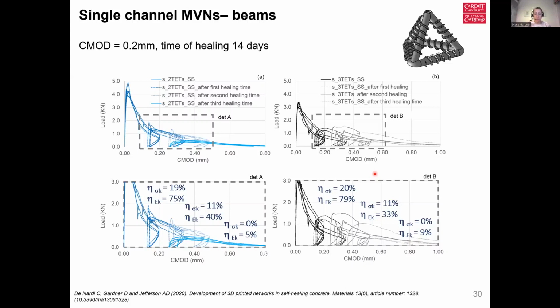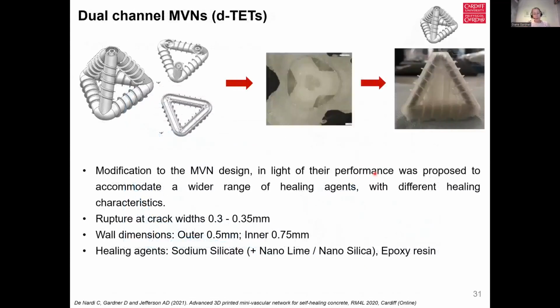Nonetheless, a recovery stiffness is still notable of 5% for our 2 minivascular network system and 9% for our 3 minivascular network system. In order to widen the applicability of these minivascular networks to a wider range of healing agents, we decided to undergo a bit of a design challenge to create dual channel minivascular networks. So they are concentric channels. It's almost like a minivascular network within a minivascular network.